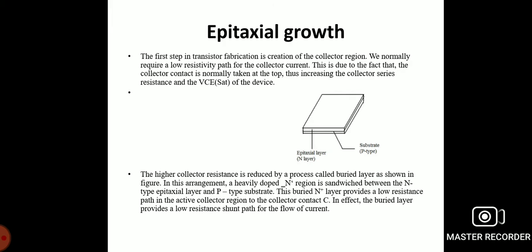We begin with a p-type silicon substrate having a typical resistivity of 1 ohm centimeter, corresponding to an acceptor ion concentration of 1.4 times 10 to the power of 15 atoms per cubic centimeter. An oxide mask with the necessary pattern for the buried layer diffusion is prepared.